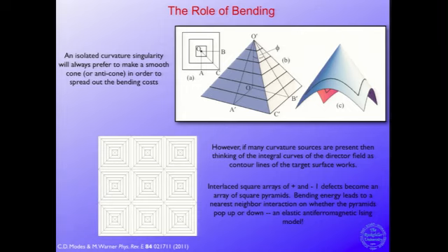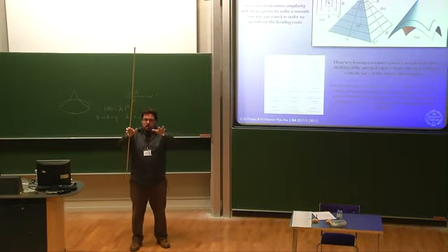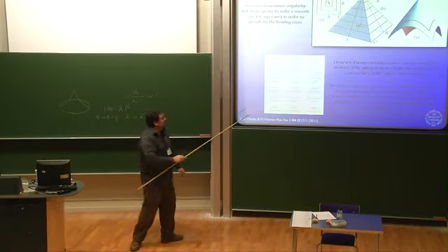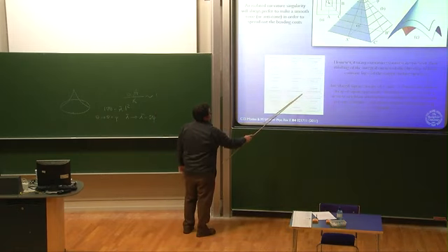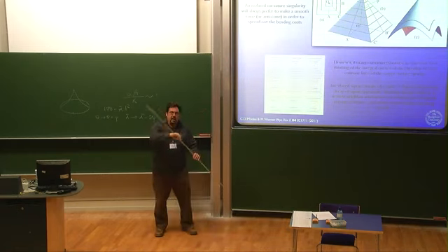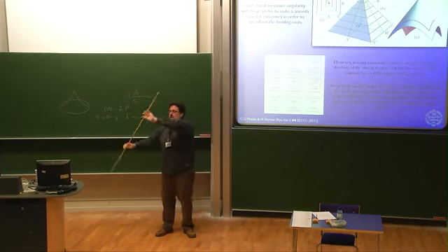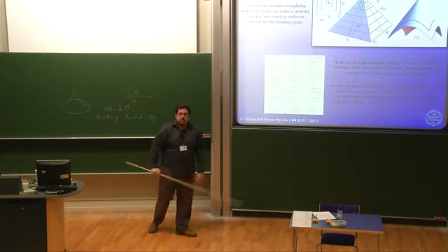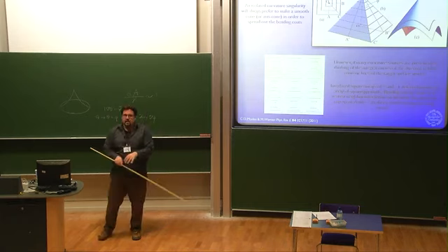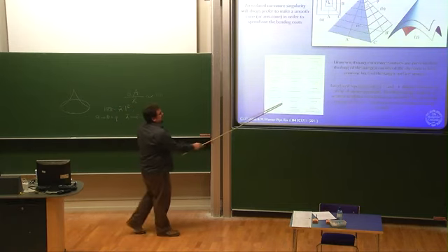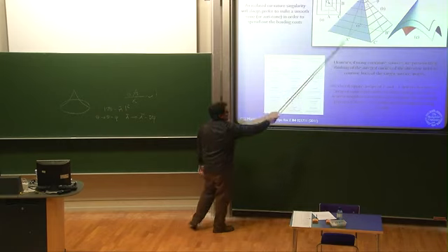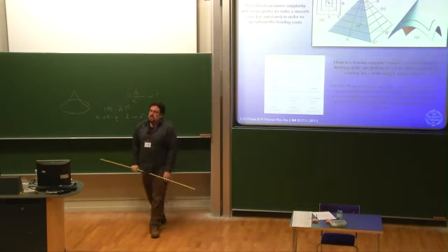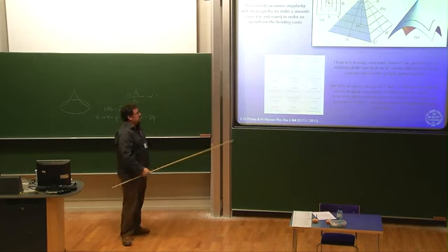And so now in this case, when you strain this, you remember in the isolated case you get the smooth cone. When you strain this, though, if you imagine the smooth cones coming up next to one another along the line of intersection, you'll get a much more complicated curve. You'll get a curve that runs up and down like this, where the cones are coming in and coming out. And that curve carries Gaussian curvature. And so you get Gaussian curvature distributed along lines if you allow this system to smooth out into a smooth cone, and that incurs a costly stretch penalty. And so that stretch,